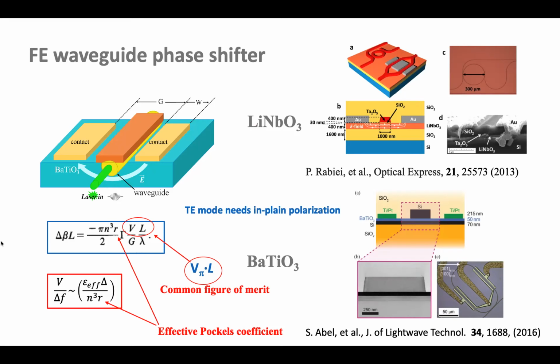What you do is change the speed of light in this path, so you can get a phase shift, right? The phase shift is directly proportional to this r, which is the thing that changes the refractive index. That's your Pockels coefficient. It's really an ugly tensor, but let's say there's an effective number which just says that if you apply a certain field, there's a delta n caused by it. And so it goes right there.